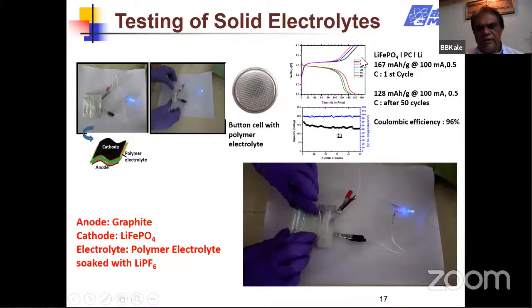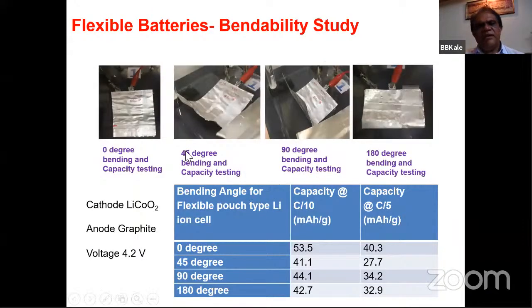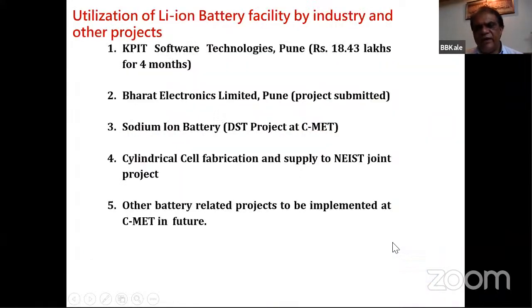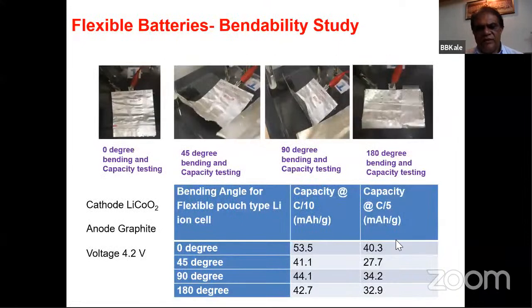Okay. And in these batteries, we have lithium iron phosphate, LiFePO4, then lithium foil. So one side is a lithium foil, another side is our material, and in between, we have polymer electrolyte. Then we did a bendable study. Very good. We tested 0 degree, then 45 degree, 90 degree, 180 degree. And you can see, though the C rate is very high, there is not much change.